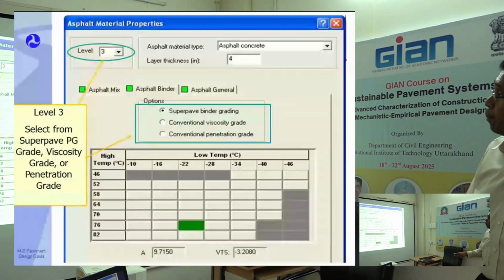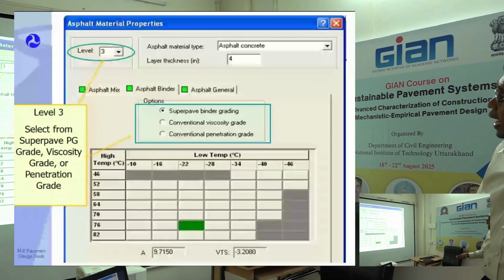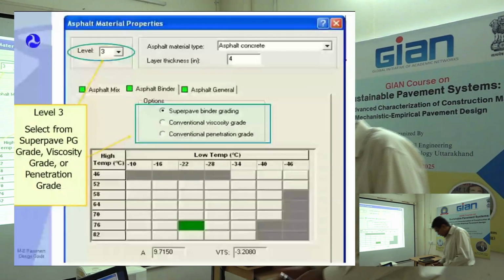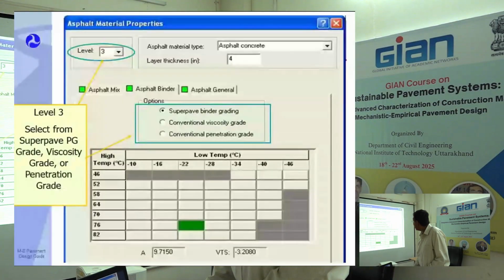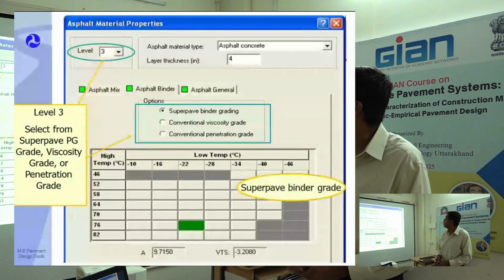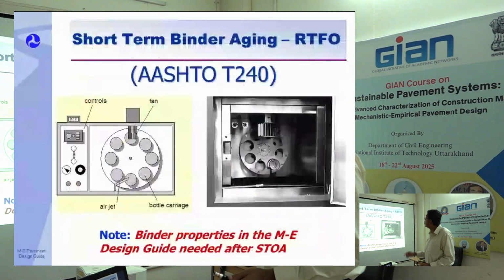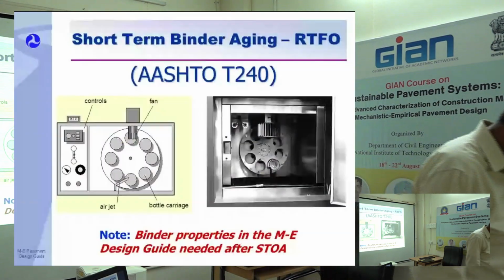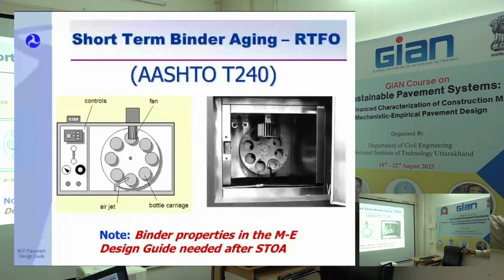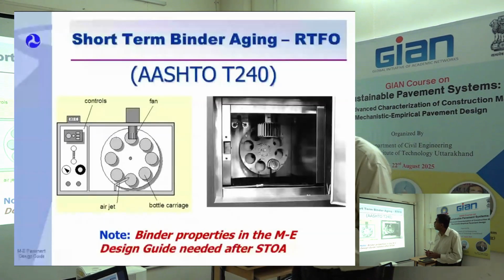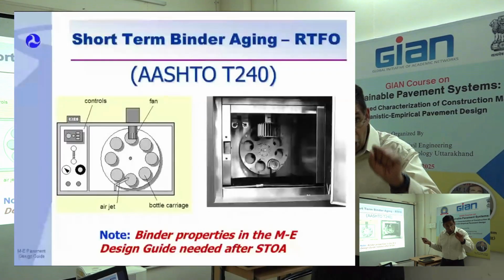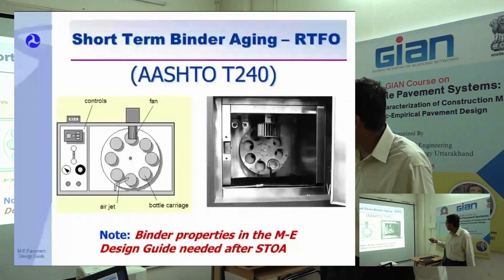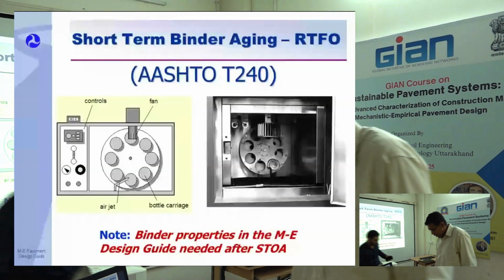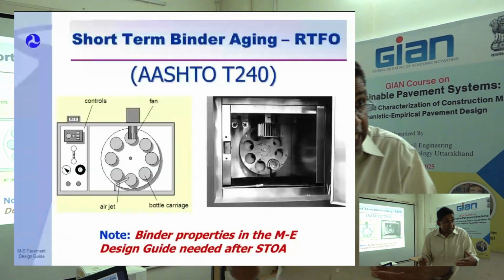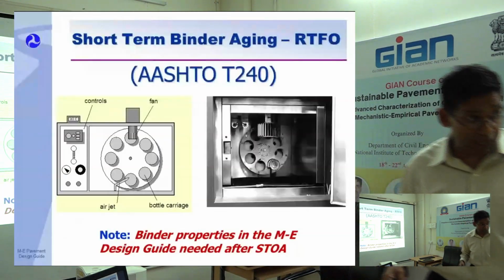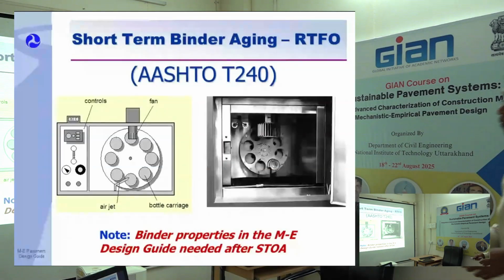Then you can use superpave binder grading, PG 76 minus 22. You can pick that and then you can get the A, VTS. Now you can use superpave binder grade. You can use other information. Then you can do RTFO, rolling thin film oven, to look at aging. So you can get the binder properties in the design guide using short-term aging. Are you aware of this? You put hot air at 325 Fahrenheit for 85 minutes. Yeah, correct. And it will age. It simulates aging during construction. That's why the word short-term aging, short-term oven aging.